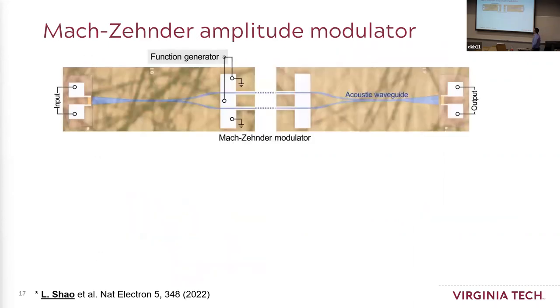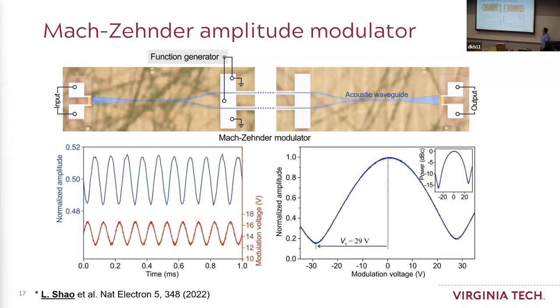And it is actually relatively easy to turn phase modulation into amplitude modulation with a structure we call a Mach-Zehnder interferometer. The way it works is that it is separated into two paths. And if you notice, the direction of the electric field is actually opposite in the two paths. If you apply voltage in the middle, the upper path will get, for example, a negative field, and the lower path gets a positive one. In that way, the phase changes they get through the two paths are opposite. So when you merge them together, interference happens. And by controlling the phase difference between the two paths with the voltage, we can control the output amplitude of the acoustic waves like this.